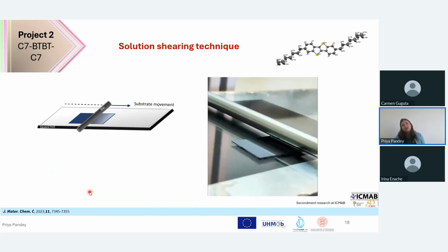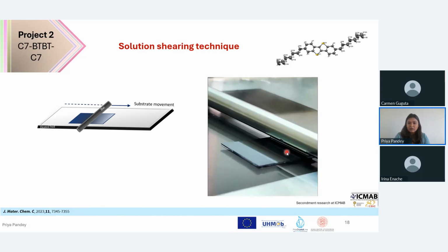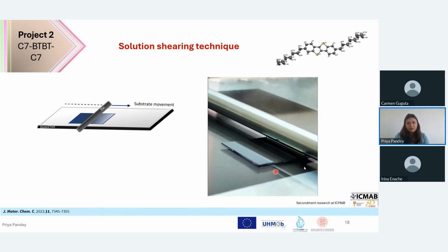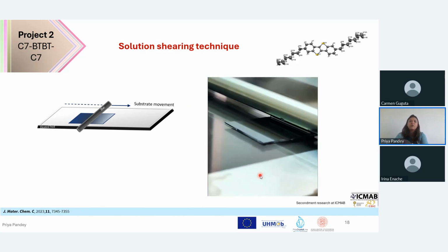Another non-equilibrium technique, or rather I can say deposition technique, I tried was at ICMAB-CSIC in Barcelona, where I used bar-assisted meniscus shearing. As the name suggests, we have a bar and we form a meniscus of our material dissolved in a solvent that it's soluble in. I used chlorobenzene. And then we can shear the material on top of the silicon wafer by moving it horizontally.